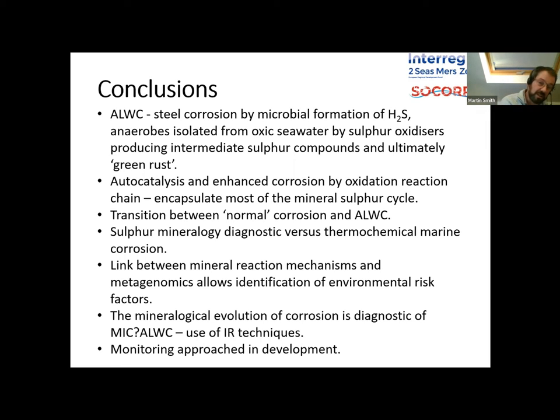When we go to sites that are affected by the microbially influenced corrosion, even when we look at material that isn't suffering from the obvious accelerated corrosion forms, we can still see the mineralogical evidence that these things are going on. And we can clearly differentiate thermochemical marine corrosion from microbially influenced corrosion using the sulfur mineralogy.